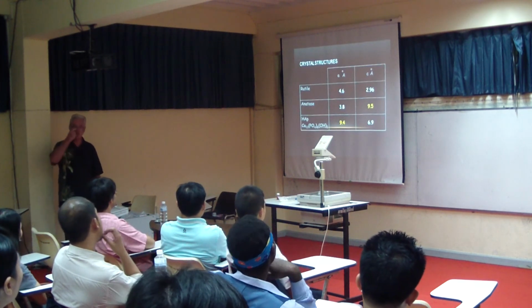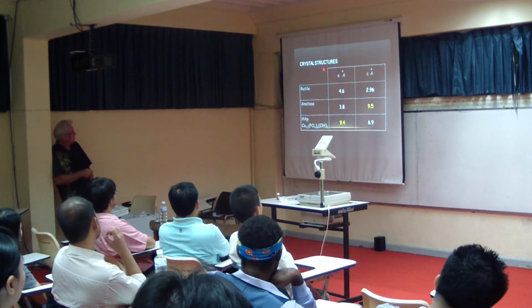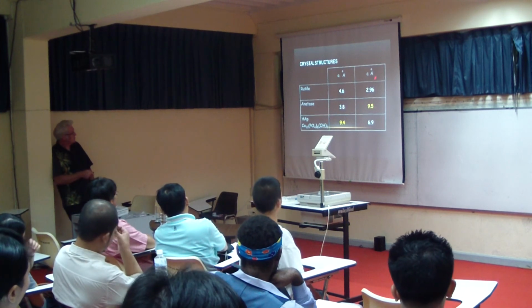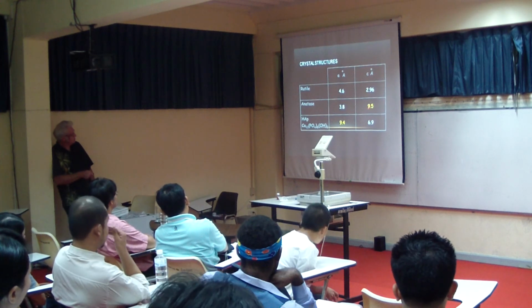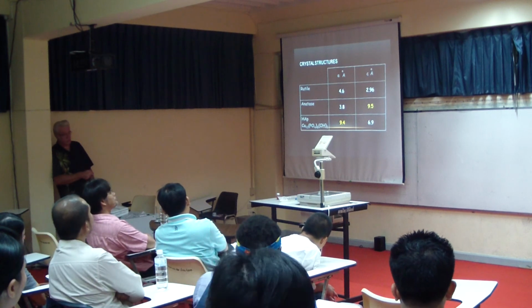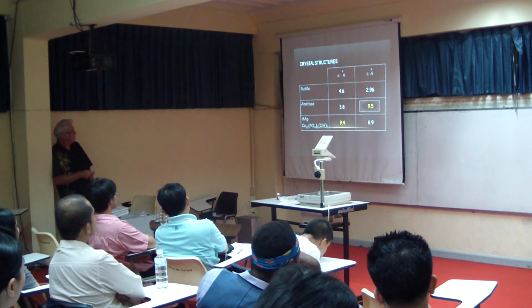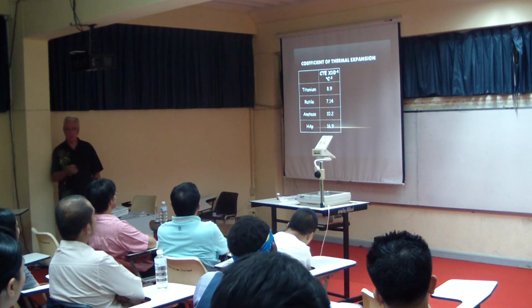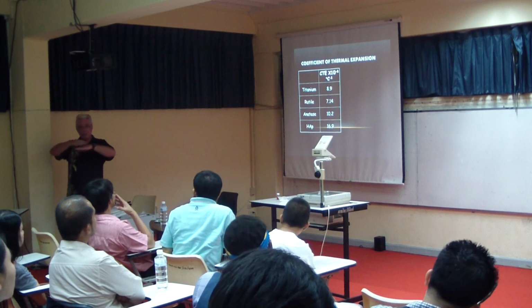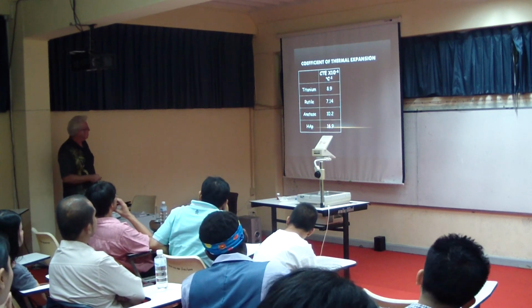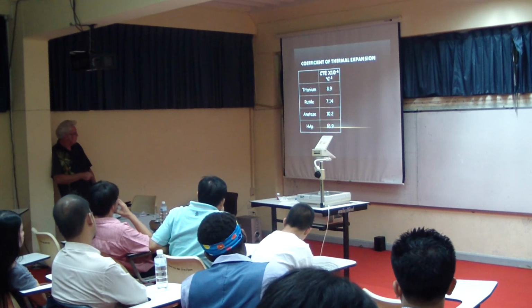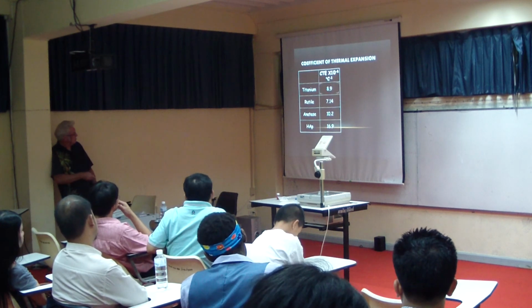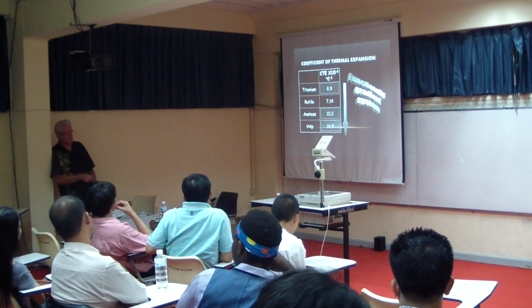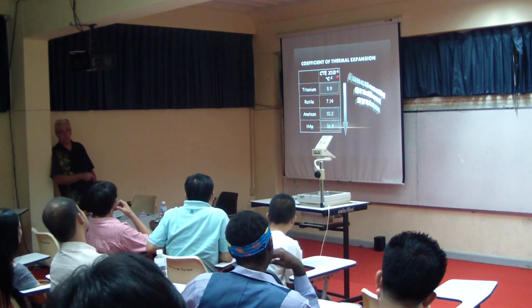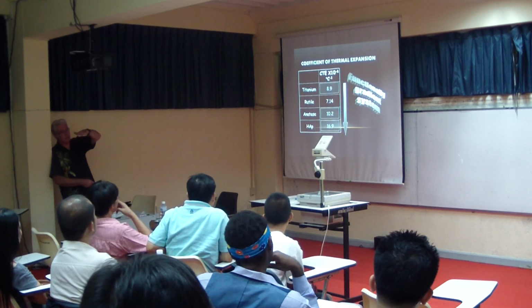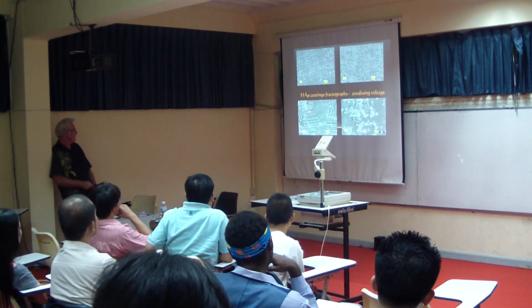The interesting thing is, and you've got to take this into account when you do these coatings, is that you've got to match things up. The crystal structure, we found that we really wanted anatase because one of its crystal sizes was about 9.5 angstroms, which compared favourably with hydroxyapatite. So we didn't get crystal strain mismatch. We also found that thermal expansion, we're going to heat this thing up to 400 degrees and then let it cool down. If the layers have different thermal expansions, we're going to get cracking. And again, we found that the titanium's 8.9, anatase is 10.2, and hydroxyapatite 16.9. So we had this, what people these days call functional gradient system. If we had a lot of rutile, we'd have a problem. Because the thermal expansion doesn't nicely increase across the width of our interface. Now these are just some fractures.